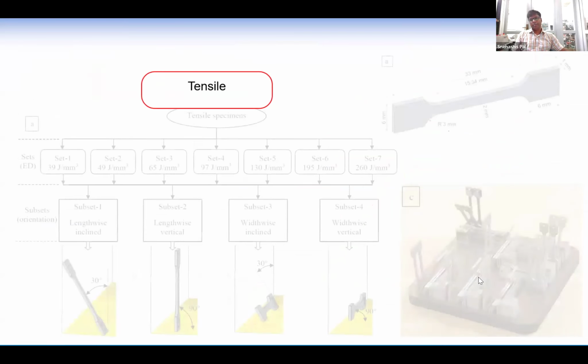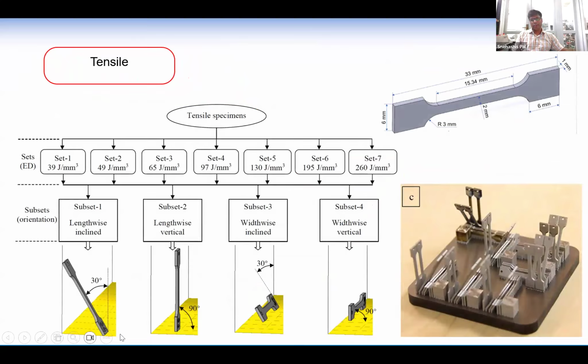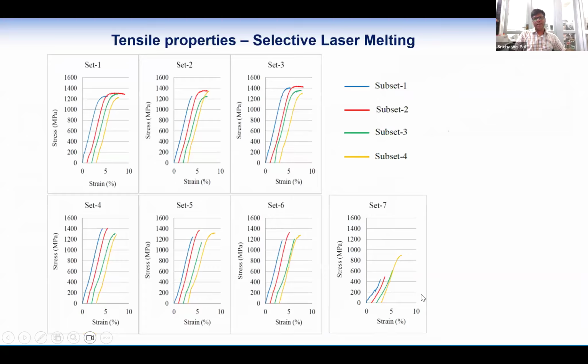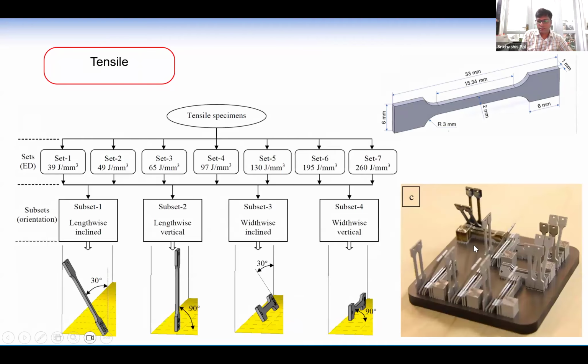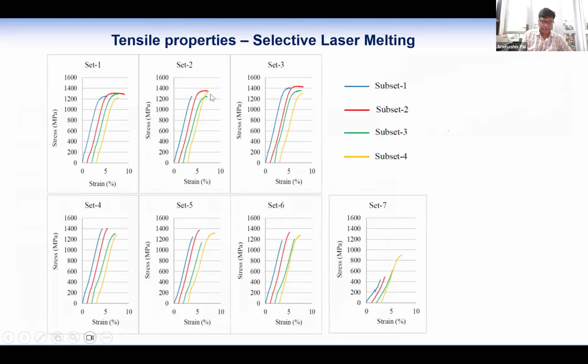And for tensile strength, depending upon the build orientation, let's say we tried these 4 types of build orientation. You can see here that the first one is inclined 30 degrees, and then also laid down, and then also inclined 30 degrees, like this way. As a result, they are okay. We used several energy densities by changing the scanning speed. Let's say this gave more or less good results. This one is the inclined, the substrate 2 is vertically built up, and this is the horizontally built up.